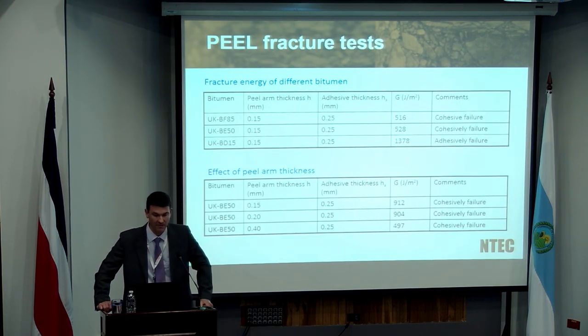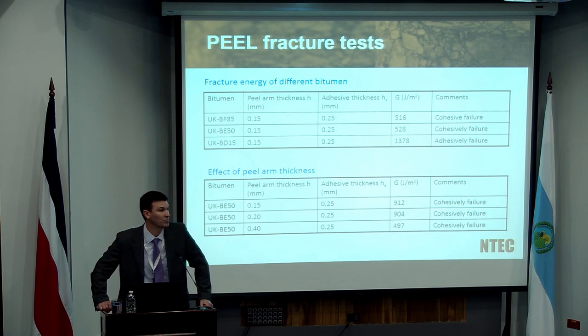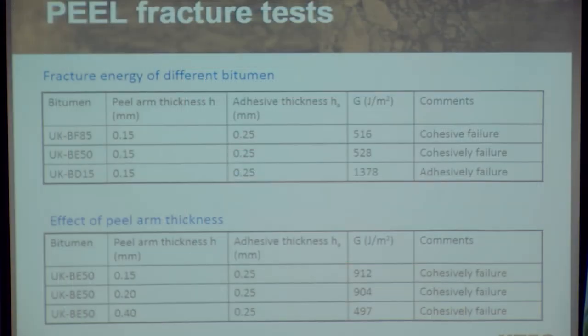I don't want to dwell too long on the individual results. But if you look at the bottom table first, I've got my three peel arms, 150 microns, 200 and 400. The 150 and the 200 gave you roughly the same kind of energy, so about 900 joules per meter squared. And that kind of indicates to us that those are the kind of thicknesses where the influence of the thickness of the aluminium plate is not going to be a factor. The 400 shows a massive difference. And what we found is that if you get thicker and thicker, you tended to actually spend a lot of the energy in actually peeling that aluminium plate and not actually measuring the binder with adhesive. And so your fracture energies have dropped down to about 500.